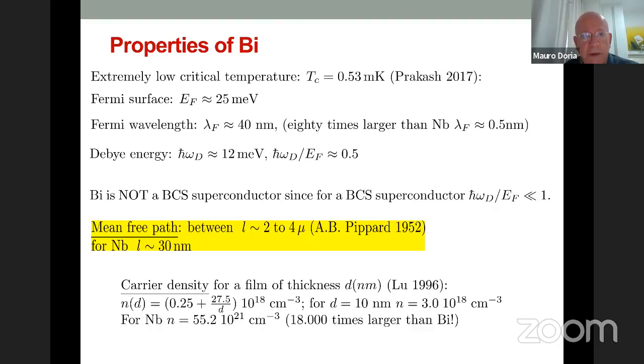Now, a little bit of bismuth, because we are going to consider bismuth and nickel. First, as I told you, Prakash, this was discovered in India. The critical temperature of bismuth is 0.53 millikelvin. It has a Fermi energy of 25 millielectron volts. The Fermi length you can obtain from here is 40 nanometers. It's say 80 times larger than niobium, which has a very small mean free path. The Debye energy, which is the frequency of the phonons, you can also discover. So what you find out is that the ratio between the Debye energy and the Fermi energy is 0.5.